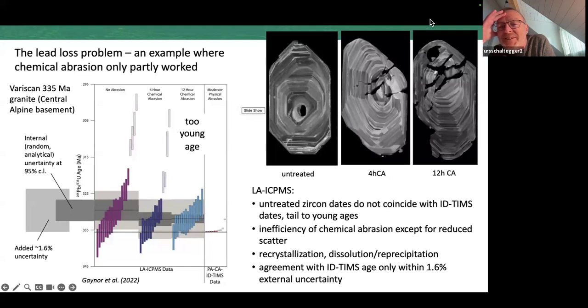And we also tried in the lab when I was a postdoc at the ROM. I remember there were some trials, and we totally failed because we did this on a non-annealed lattice. So from the better crystallized portions, we had this selective leaching of some elements, and from the portions with higher degree of damage, of course, these ones we probably dissolved already. But you make a lot of artifacts when you do not anneal. So really the breakthrough of Jim Mattinson was to realize, okay, we first have to anneal to stabilize the portions of the grains which are at the first percolation point. This was the massive advance.